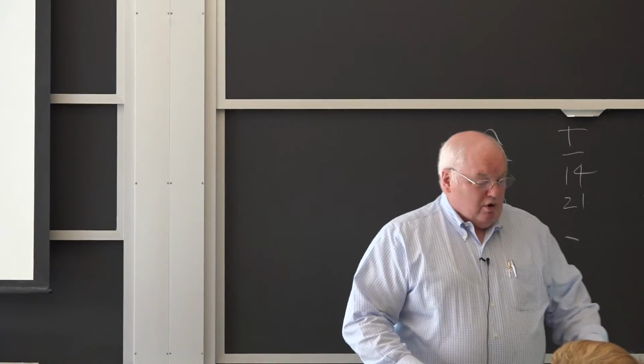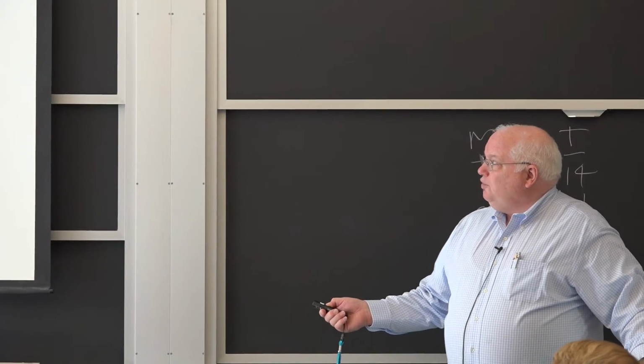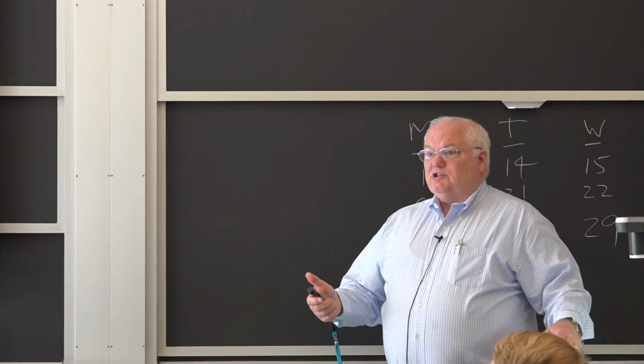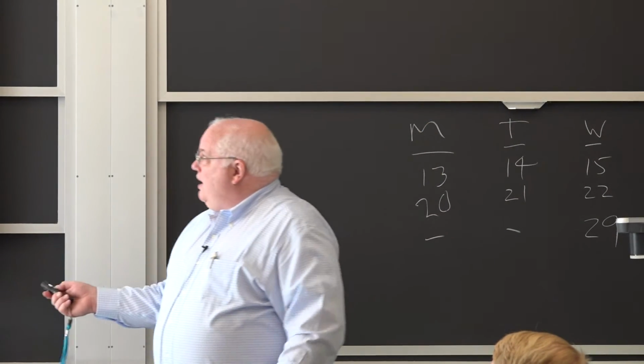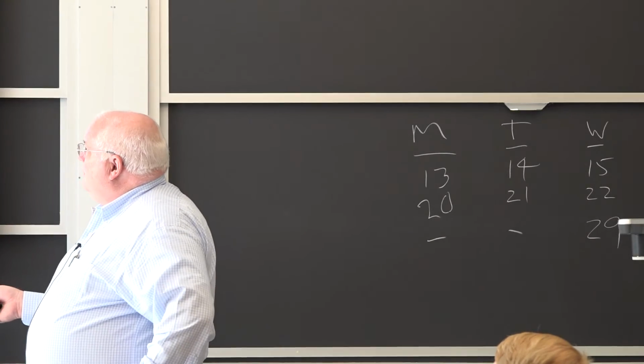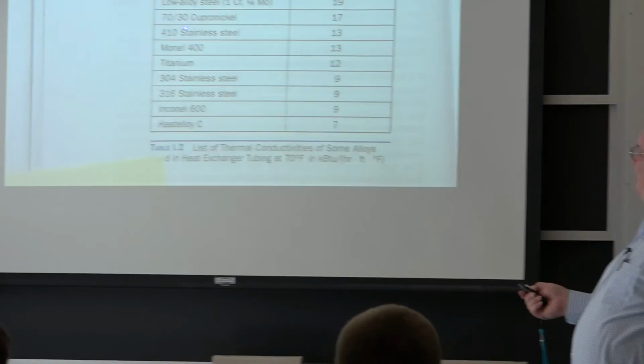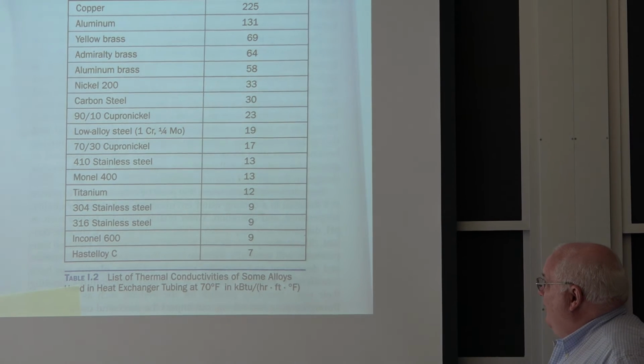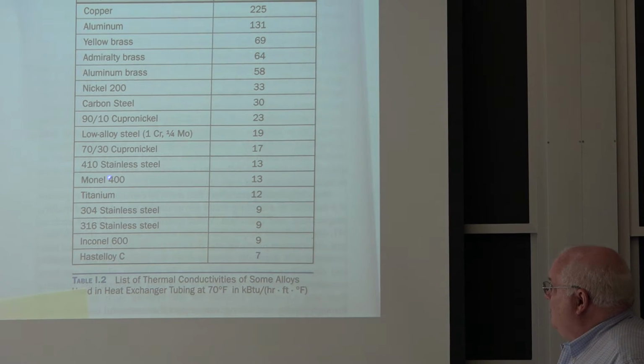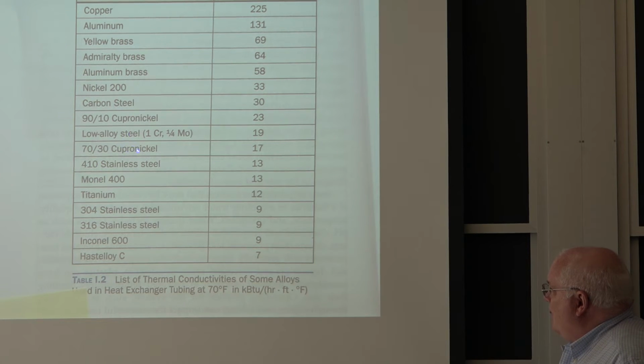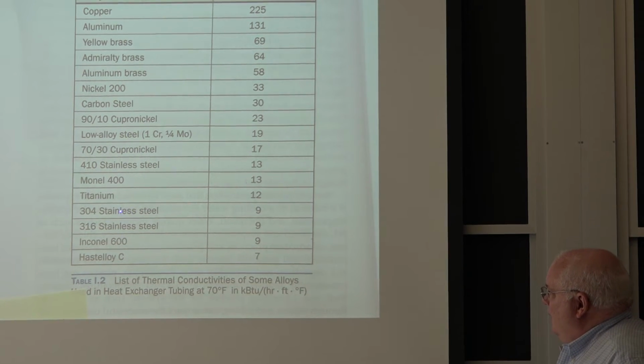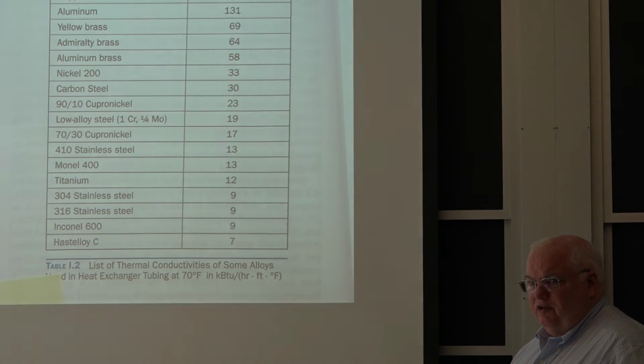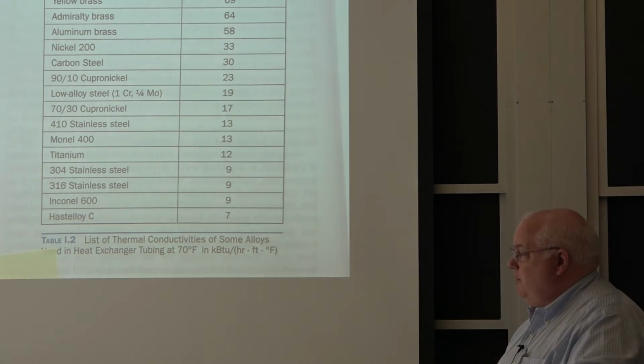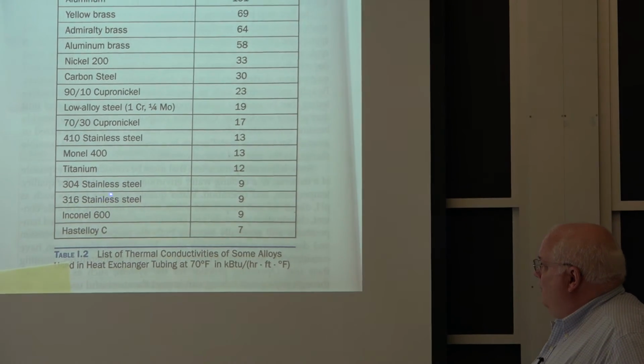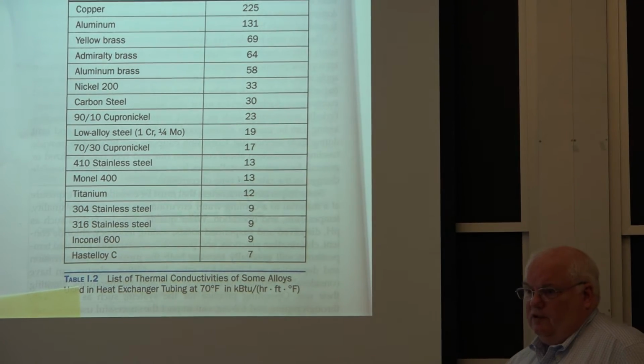So, and more, the Navy is starting to go towards titanium for piping, because now you have 50-year ships. Not when you had 30-year ships, then you would use carbon steel for your seawater piping. But now they started going to some of these higher alloys, copper nickel alloys. They never would have gone stainless steel because it'll pit like mad if you get any dirt in there very quickly. That's the problem at the New England Aquarium in a sense. But now they're even going titanium because we're looking for 50-year lives.